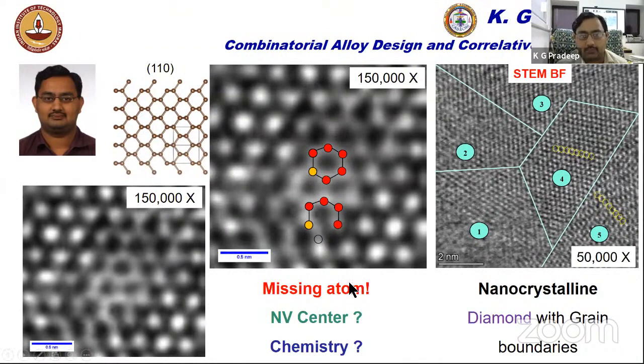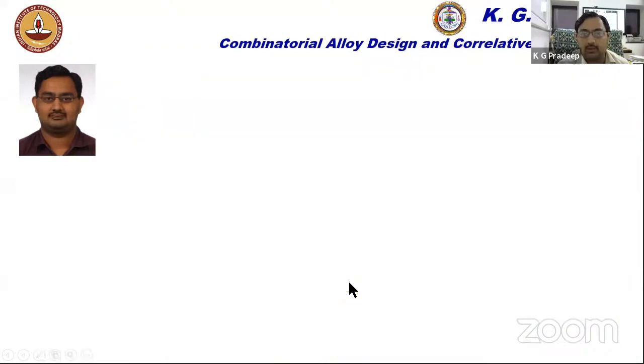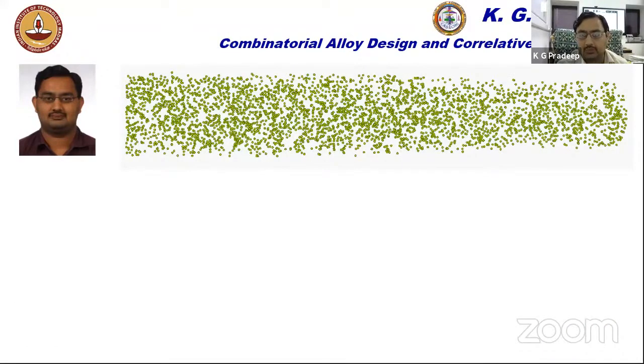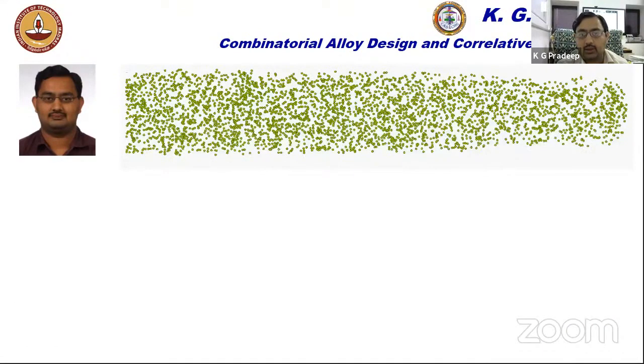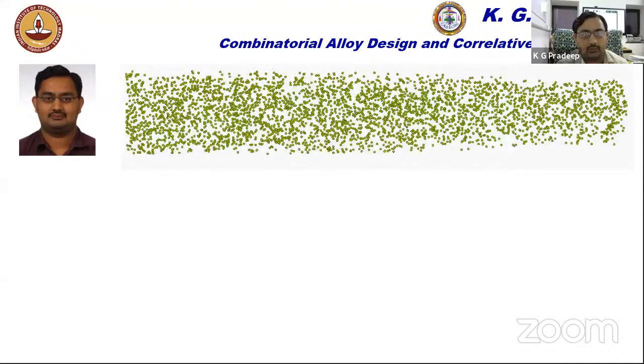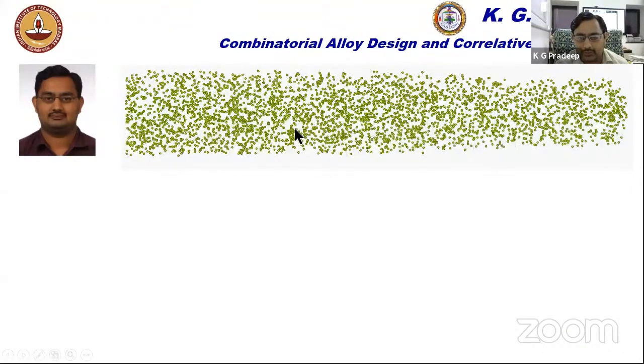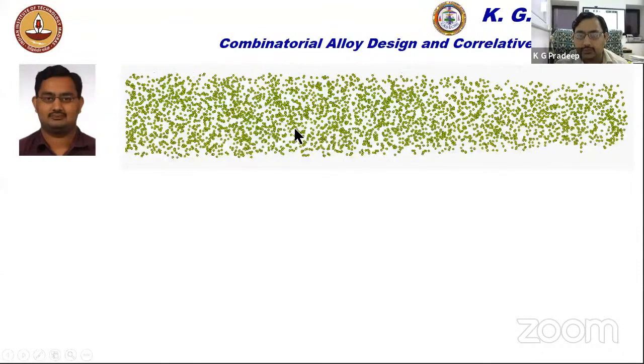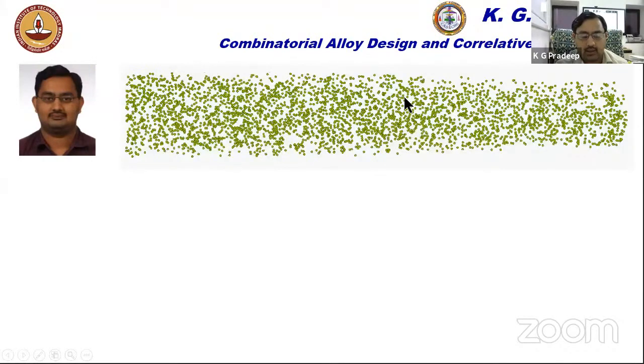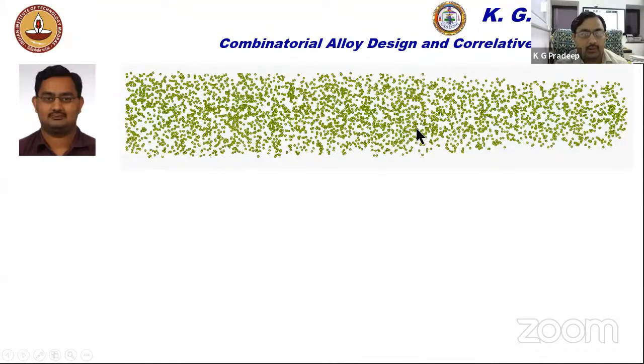Now comes the atom probe tomography, if you really want to identify where those atoms are. So now this is atom probe tomography data, which shows only the nitrogen atoms, just to give a clear impression. Now you see here, there is a random distribution of nitrogen atoms everywhere. And if you look at the length scale, these are all in a few nanometer range.